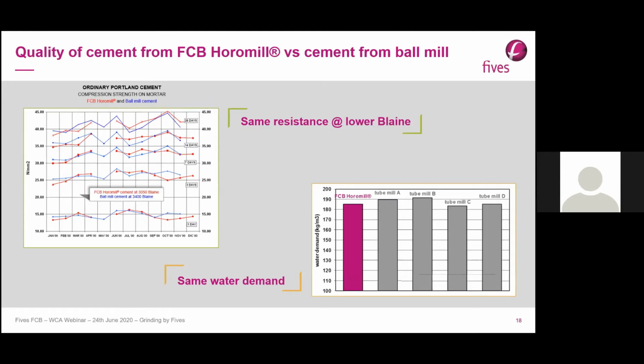But it is interesting to note that the same quality is obtained with a cement, Horomill cement, but has a lower Blaine than a ball mill cement. Typically, there is a difference of roughly 300 Blaine. So to summarize, the same quality of cement is reached with Horomill with about 300 Blaine less compared to ball mill. Just note the values here are not only a small test value, but are average values from statistics over 1 year of production, so it's representative.